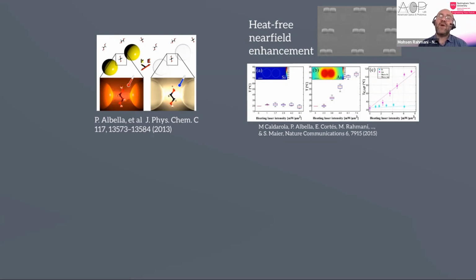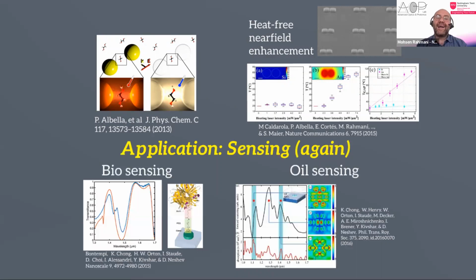So just imagine that if you have some sensitive material, sensitive cells or molecules or DNA or something on the top of your plasmonic nanostructures, this heat can damage them. So that's why it is a problem for using those plasmonic nanostructures for sensing. Also, plasmonics can give much more sensitivity, but this heating is something for us to consider when we are thinking of the sensor. That's why sensing application with dielectric nanostructures became hot again. I say again because first the sensing by plasmonics was a very hot area, then sensing by dielectrics was a very hot area. But I want to emphasize that here, as you see, we are not really using much hotspots.